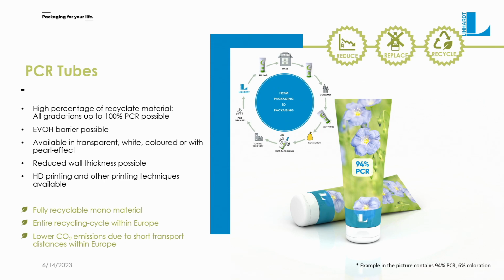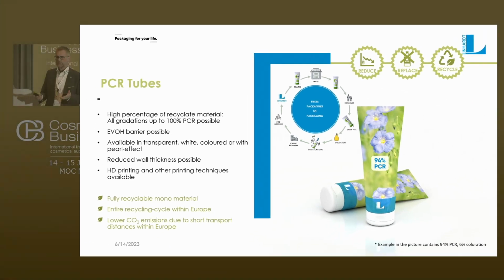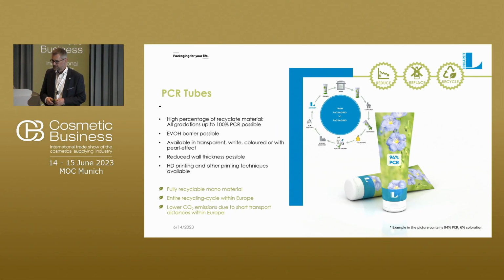With the PCR tubes, still, we can use EVOH barriers, and you can have them transparent, white, pearl effect. You can reduce wall thickness, that's very important, but you need the right recyclate with small granule sizes in order to be able to reduce the amount of inclusions or to be able to hide them better in the tube shoulder, for example. HD printing and other printing techniques are all available. You can use fully recyclable monomaterial, and generally speaking, you can feed it into the general recycling stream here in Europe.